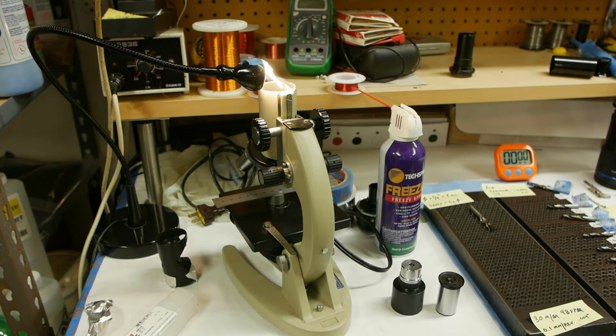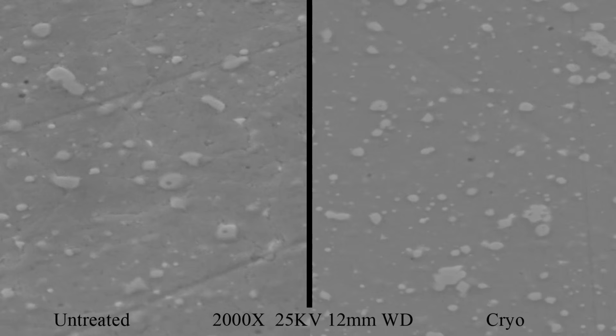Additionally, these drill bits are made from high-speed steel, which has molybdenum and chromium in there, which also forms carbides, like chromium carbide, molybdenum carbide. And those are especially good. Those are like really hard rocks to really hold the thing together. So anyway, the carbides seem like they're about the same, treated versus untreated. But certainly this grain boundary missing thing is weird.